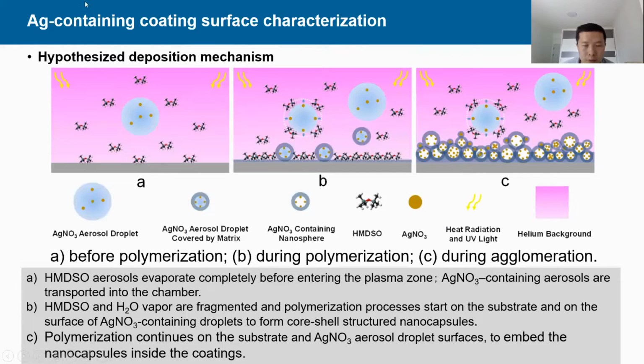So based on the previous results, we hypothesized the deposition mechanism of aerosol-assisted plasma deposition. In the first stage, stage A, before the polymerization, aerosol droplets containing silver nitrate are transported by helium gas flow into the chamber, while HMDSO aerosols evaporate completely before entering the plasma zone due to its high volatility, resulting in no nanocapsules formation in the coating.